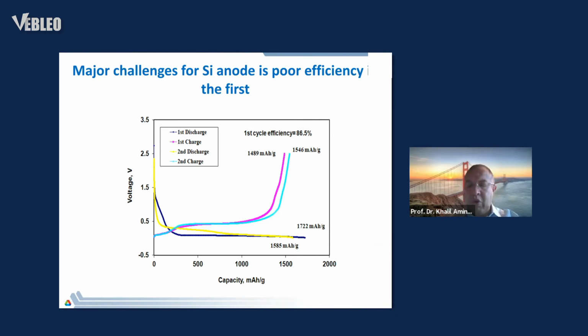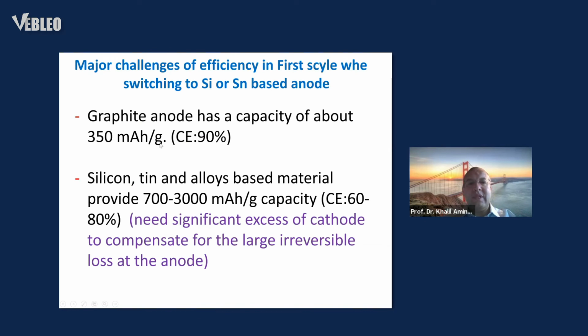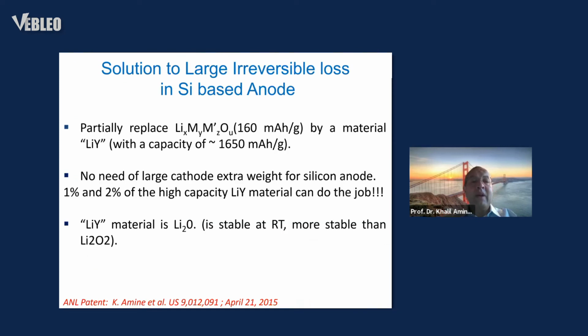Now, if you have a small amount of irreversible loss, like in graphite, you can use excess of cathode, as you can see here. But if you have a large amount of irreversible loss, then it's difficult to use a lot of excess of cathode, because cathode is expensive and heavy, so it defeats the purpose. So you cannot do that. You have to come up with a pre-lithiation technology, and that's exactly what we've done.